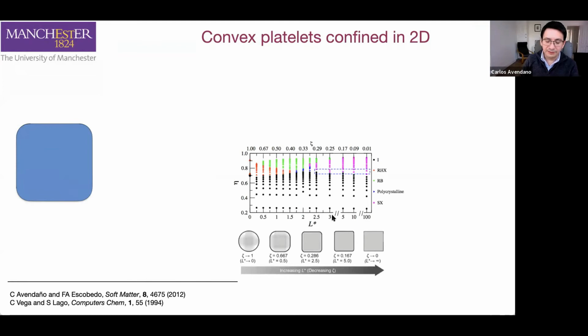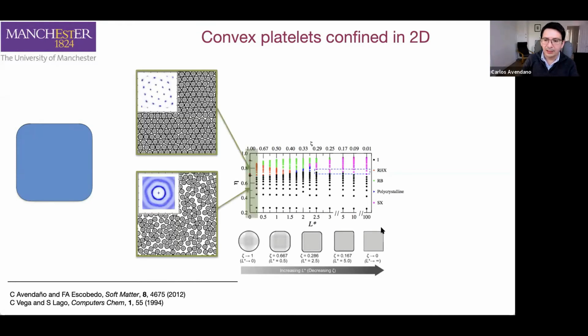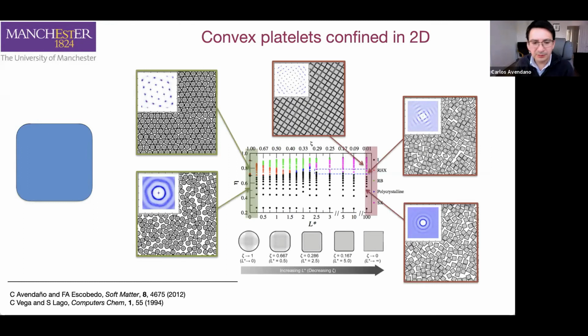Using this model and using computer simulations in Monte Carlo simulation, NPT ensemble, we managed to get the entire phase diagram. The first thing that we did is to check, obviously, that the model reproduces the two extremes, the perfect disk and the perfect squares. And we observed that the model reproduces that. So we observed that the perfect disks form the isotropic phase and the hexagonal phase. And for the case of the perfect squares, we see that at low densities, we form again this isotropic phase.